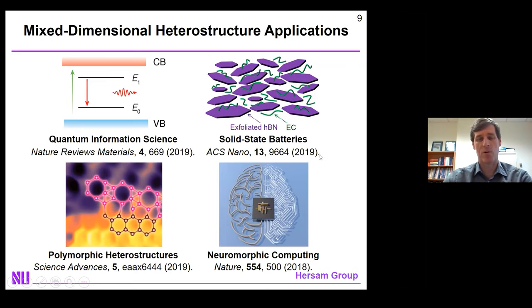We've also been pushing the concept of polymorphic heterostructures, in this case between borophene and graphene, where we exploit the polymorphic bonding that can occur in 2D systems like boron to achieve lateral heterostructures with atomically sharp interfaces, even though the materials are not lattice or even symmetry matched.